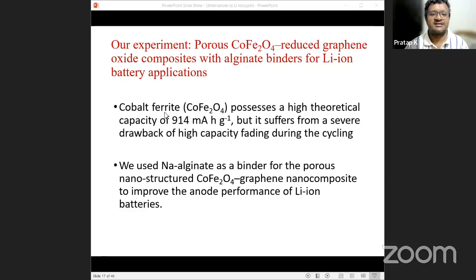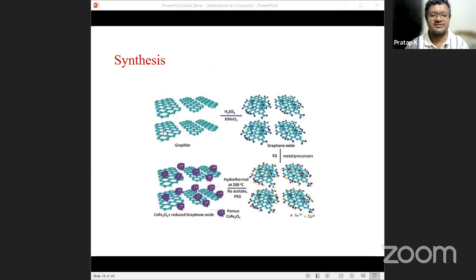So the theoretical capacity value of cobalt ferrite is 914 milliamp hour per gram. And we have used sodium alginate as binder. So this is mentioned here. So this is the synthesis procedure, graphite. So this is the advanced Hummers synthesis procedure. And graphite is changing into graphene oxide. So we have added metal precursors, and after adding the metal precursors and following the hydrothermal route, so this is the graphene oxide. The blue one is the graphene oxide, and the violet ones are the cobalt ferrite nanocomposites on it. So cobalt ferrite nanocomposites are anchored onto the reduced graphene oxide flakes.